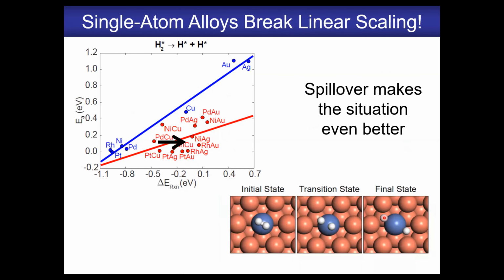Now, if the hydrogen can spill over from the final state here onto the copper surface, the situation gets even better. For example, if that's palladium copper there, if the hydrogen spills over, it'll have binding strength similar to pure copper, which is here. So it'll actually move this point all the way to there. So you'll have even weaker binding to the hydrogen and a low dissociation barrier for the activation of the hydrogen.